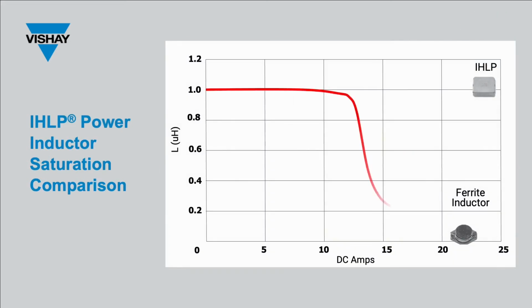In terms of the saturation characteristics of the IHLP compared to a standard ferrite inductor, there's a drastic difference in performance. The red curve illustrates a typical ferrite inductor as the current is increased for a given inductance value. The curve is very flat up to a certain current level, known as the saturation point, at which there is a significant drop in the inductance. As the current continues to increase, the inductance continues to drop until the inductor behaves more like a resistor, which is obviously not the desired result in most power supply or filter designs.